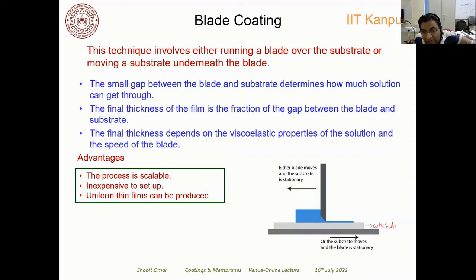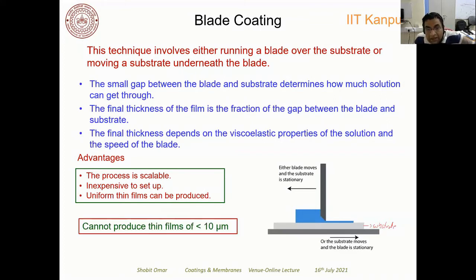This process is scalable, but this cannot be used for a curved surface, and this is an inexpensive process. You can set it up in your laboratory, and you can make a uniform thin film on the substrate. But you cannot make it on a complex component with a complex structure. Also, you cannot make film with a thickness of less than 10 micron using this process.